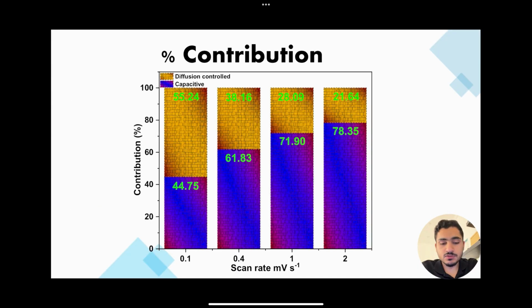Finally, we have the percentage contribution, where the battery can be either diffusion controlled or capacitive controlled. At a scan rate of 0.1 millivolt per second, the battery showed a diffusion controlled behavior of about 55%. When we increased the scan rate to 0.4 millivolt per second, it showed a capacitive controlled behavior of about 61.8%. When we increased the scan rate to 1 and 2 millivolt per second, the capacitive percentage kept increasing.